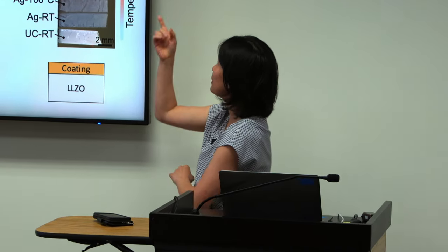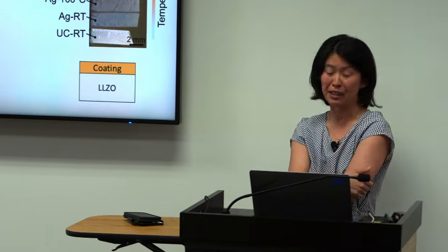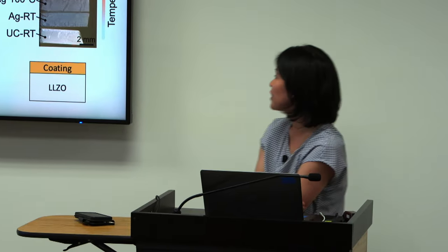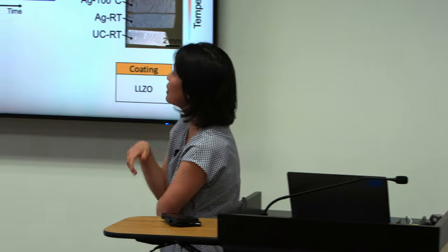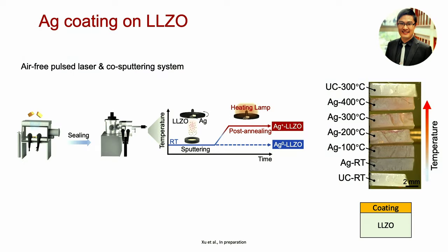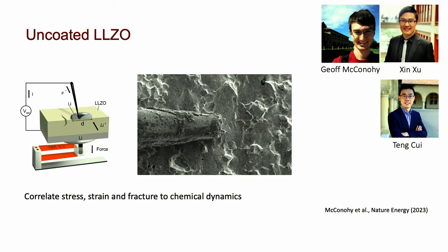This is work that was headed by Xin, who's a postdoc from Will's group and is now a professor at ASU. What he did was take LLZO and deposit just a very thin layer of silver, about 3 nanometers. Then he heated up the silver to different temperatures and measured the properties, anywhere from room temperature up to 400 degrees.